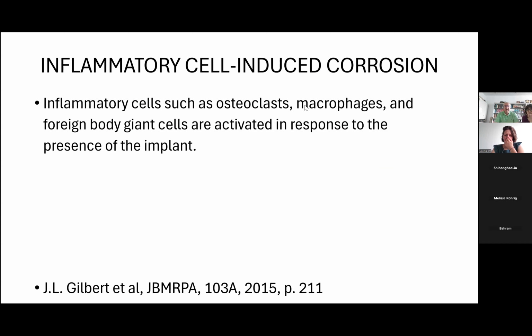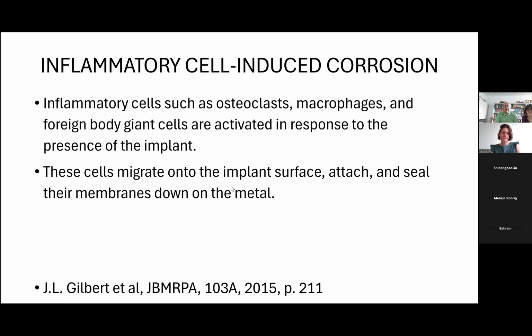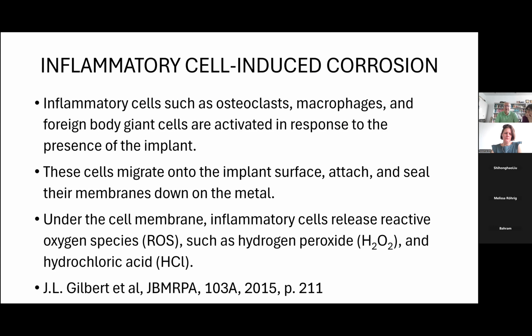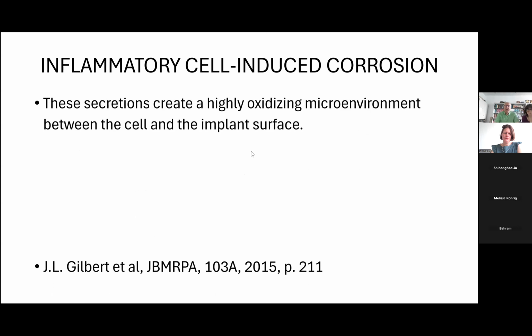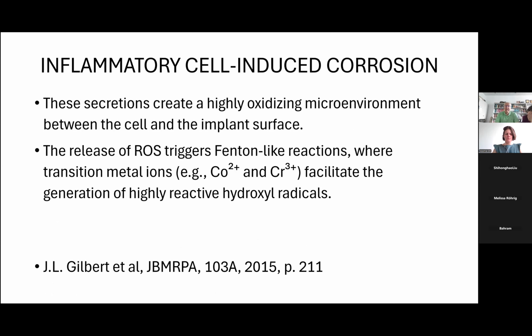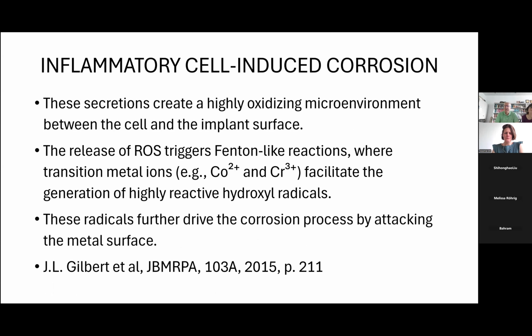It means you have the osteoclasts, the macrophages, and they are activated because you do have a piece of metal. These cells migrate on the surface of the metal and attach, and you have a sealing of the membrane of the cells on the metal. And under the metal, you start to see some oxygen species, for example, hydrogen peroxide, and even hydrochloric acid, which I thought was very, very strange. And after, this secretion creates a highly oxidizing microenvironment. And after, you have a kind of Fenton-like reaction. To be honest, I don't understand what a Fenton-like reaction is, but it is maybe due to my bad knowledge in this field. And at the end, you have a corrosion of the metal.